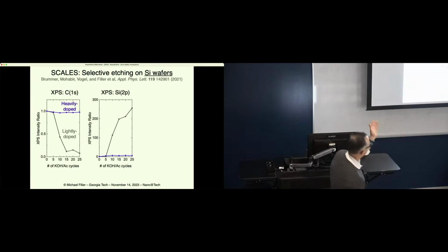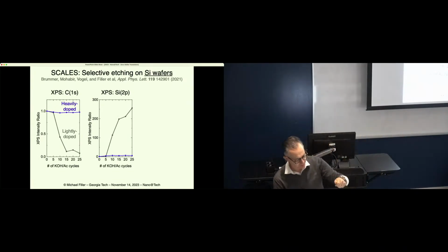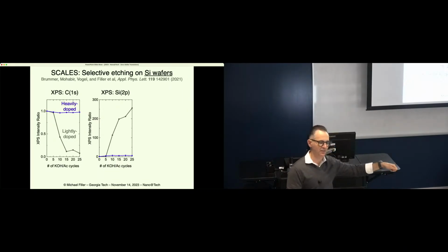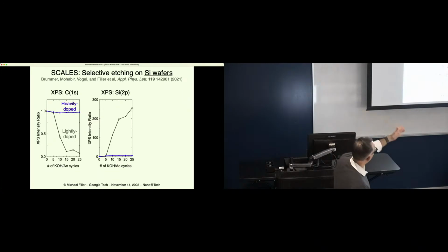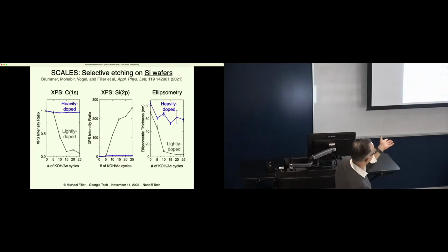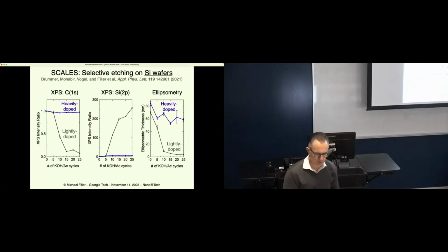So we can track this as a function of cycles. We do this process by which we do some KOH, and then we dip it basically in a developer of sorts to get some of the chains out into solution. And we can track this, and it goes as you might expect, right? So we have basically no change in the carbon 1s for the heavily doped region, and in the lightly doped region, we remove carbon. And we can track this with another technique like ellipsometry, and the story is pretty much the same.